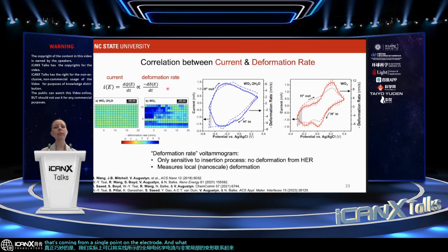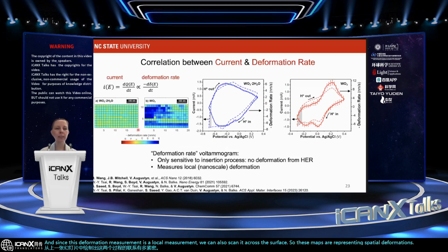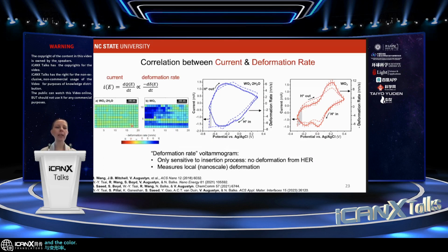And what we did here is we simply took the derivative of the deformation, the derivative with respect to time of the deformation from the previous slide, to map out how closely those two processes are linked. And since this deformation measurement is a local measurement, we can also scan it across the surface. So these maps are representing spatial dimensions along X and Y with the deformation rate, and the color indicating the degree, or the intensity, of that deformation in different regions.